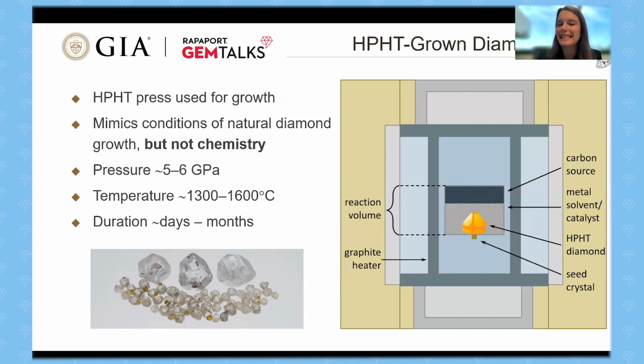So here on the right, you have an example of a little cartoon showing the inside of this reactor. So you have a little diamond seed. In order to grow any type of diamond, you have to start with a little piece of diamond as a template. And then above that, they have a mixture of metals, the source of carbon. They heat it up. The carbon dissolves into the melting metal, recrystallizes this new diamond onto the seed, and that gives you your HPHT diamond.